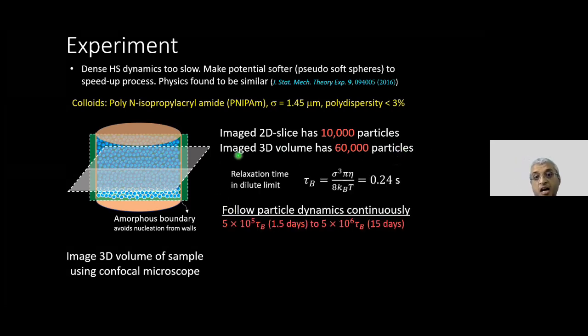Okay, and now the relaxation time, so you can trivially evaluate it. In a Newtonian liquid, the relaxation time is about 0.2 seconds. And now we are going to follow particle dynamics as it attempts to crystallize. So we're going to have this glassy sample as it attempts to crystallize. We're going to follow dynamics from about 5 times 10^5 tau_b, which is 1.5 days, to 5 times 10^6 tau_b, which is 15 days.